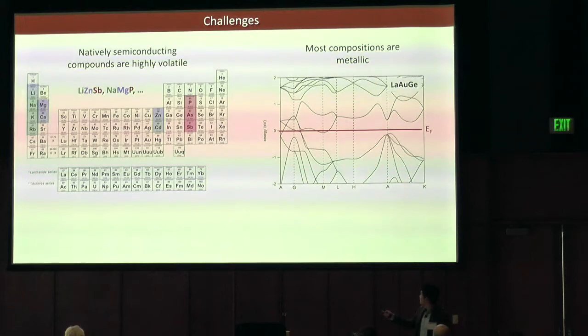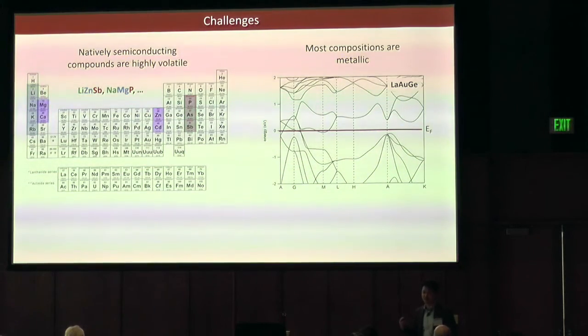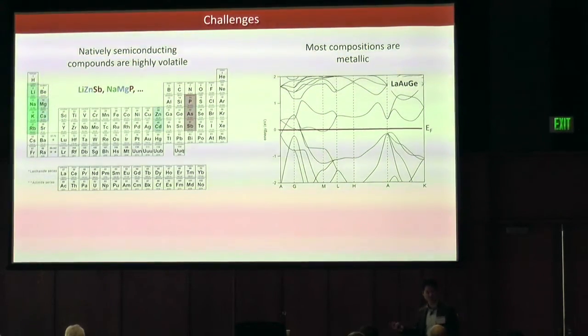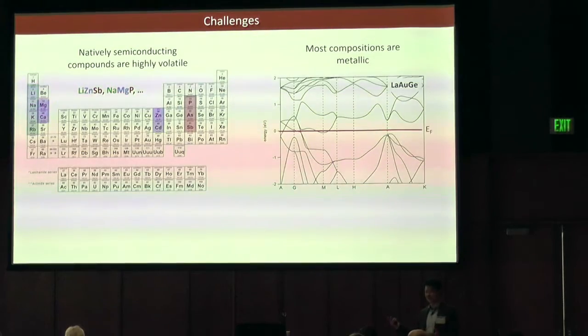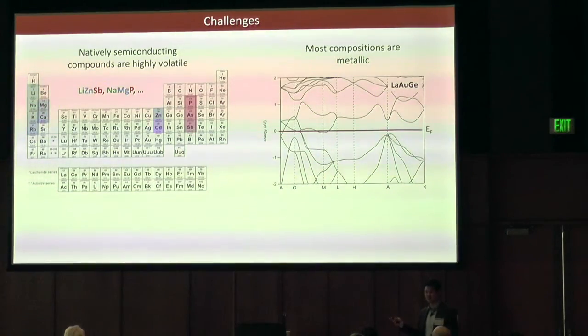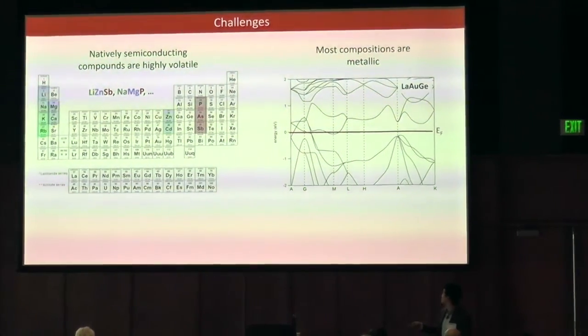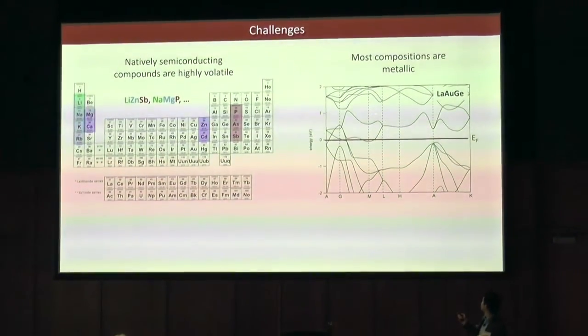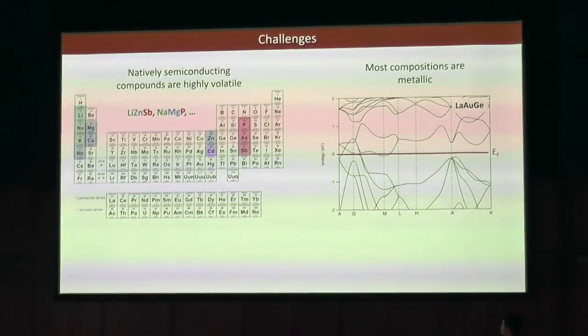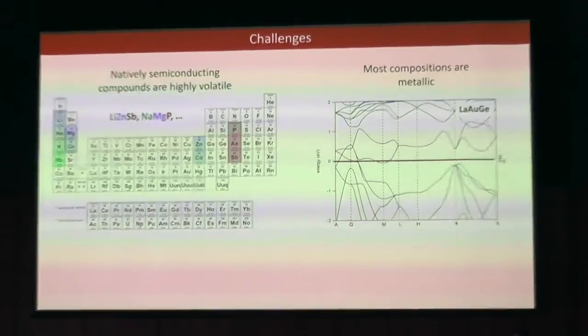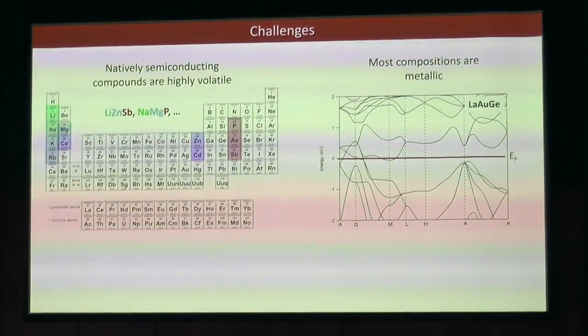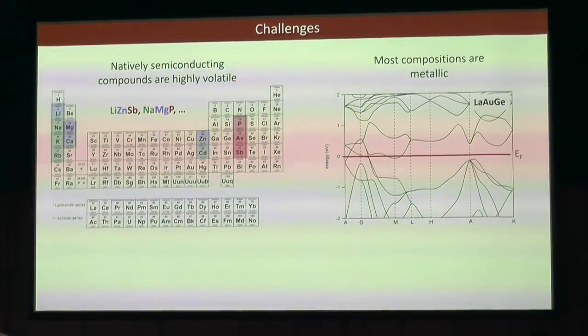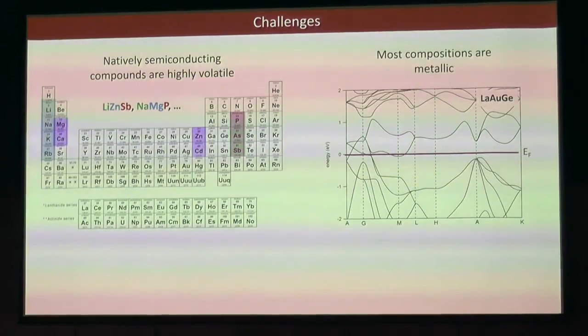I'm an MBE grower. I generally don't want to put lithium and zinc into my nice, clean III-V MBE system, okay? So I generally want to avoid that at all costs. Another challenge is that although some were specifically predicted to be ferroelectric, many of these compounds are actually natively metallic. So what are we going to do about that?